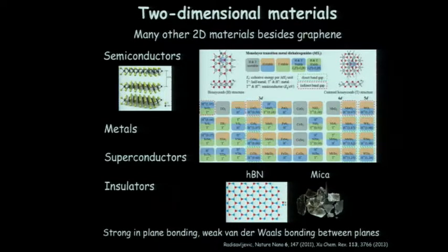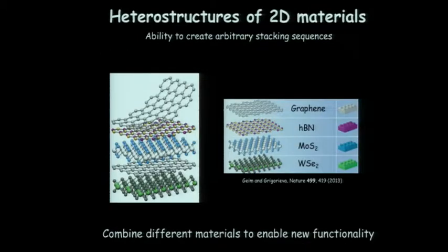And so these materials all have one thing in common with each other, which is that they have strong in-plane bonding and weak out-of-plane bonding, so that we can isolate them down into, in the case of graphene, monolayers. And for the rest of the materials I'm going to tell you about, they just need to be thin materials, and we're going to look at those. And so this is then sort of the picture of what we want to do. What we've been doing in my lab for now, I guess it's almost 5 years, is taking graphene and coupling it with other materials, kind of like Legos, and seeing what kind of new functionality we can enable by mixing and matching these materials together.